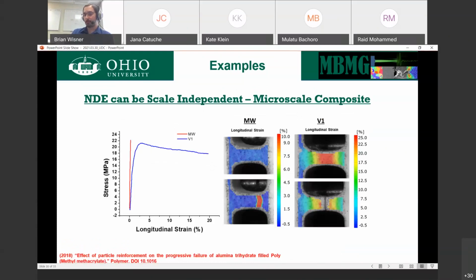It's not metal specific. The point of showing this is the use and the power of the methods in order to improve material properties. So this particular example was a question that DuPont came to us with and said, hey, we have this material. It behaves in a certain way, this red line. We're trying to make it more damage tolerant. Can we characterize what's happening to this material so that we can make informed decisions about how to alter the structure? So what we did was take this, we applied the load, we did this first at this scale in order to prove that there isn't any significant out of plane motion, to prove that microscale investigation can work.